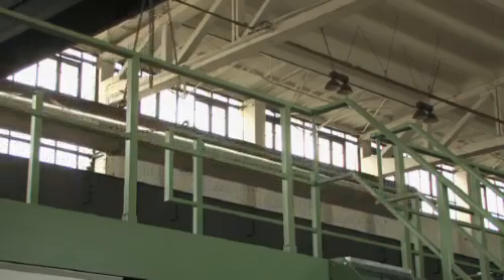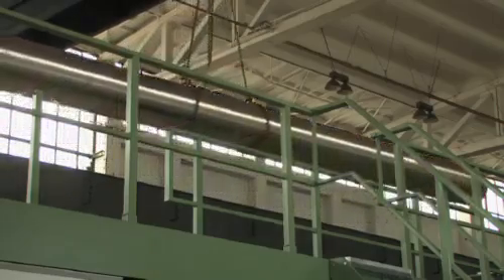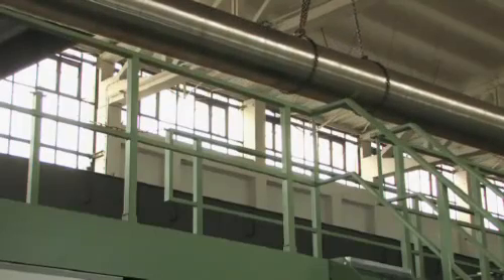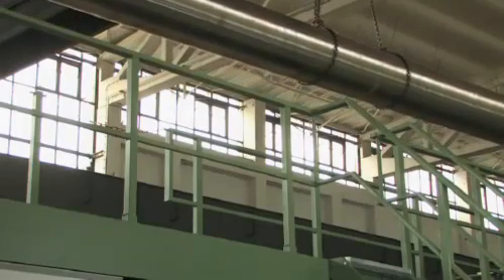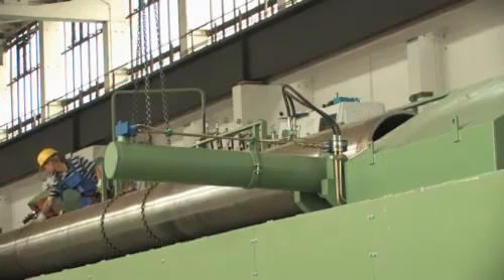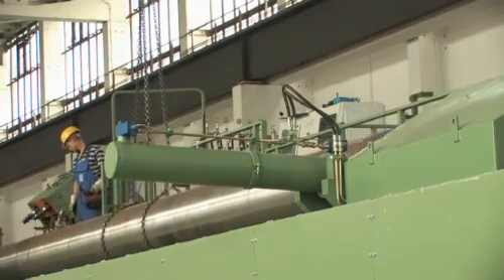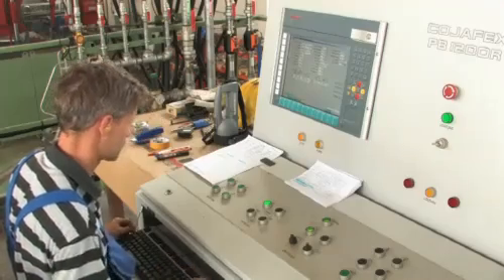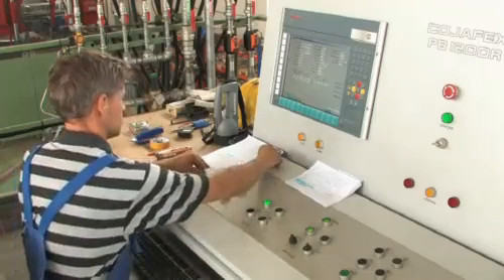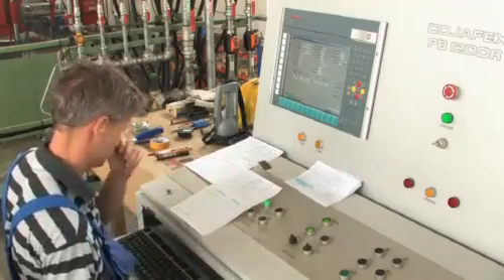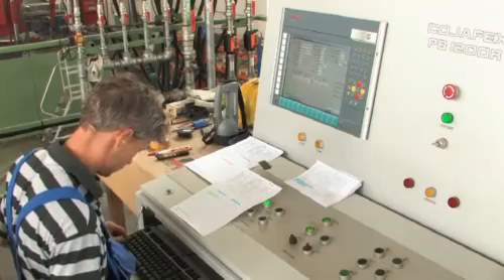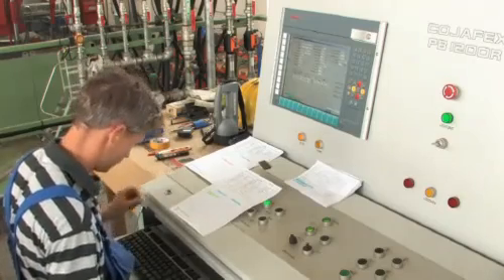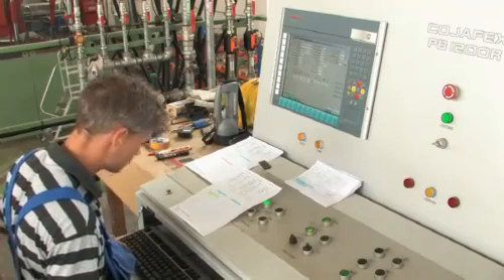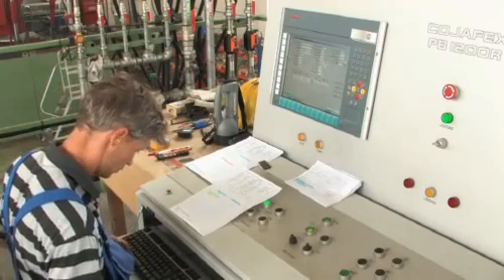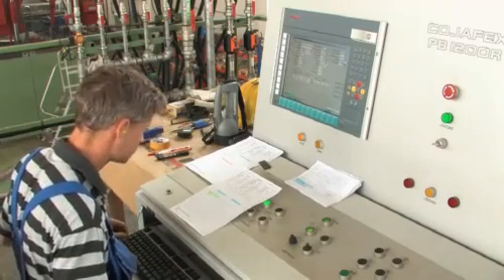A heat-resistant pipe of type P92 quality with an outer diameter of 590 mm and a wall thickness of 26 mm is inserted into the machine. The bending of a 54.1 degree angle is already completed. Now bending has to be performed at a 90 degree angle. The bending radius is equal to 1,700 millimeters. The operator adjusts the process parameters and starts up the plant.